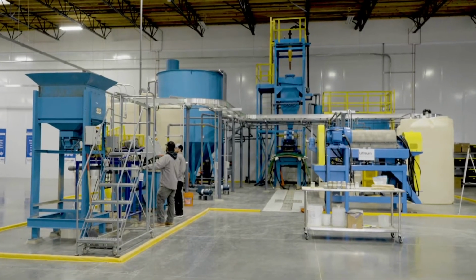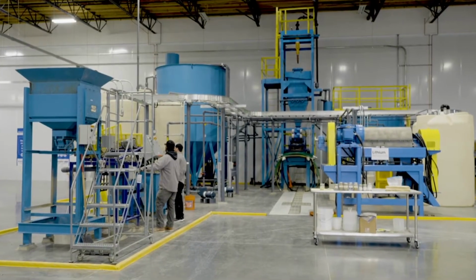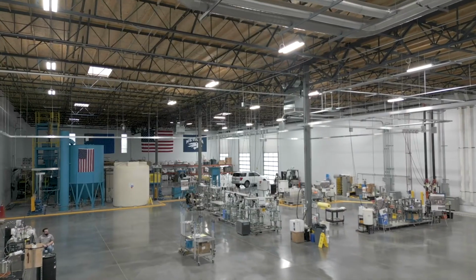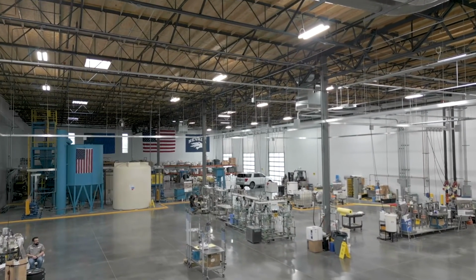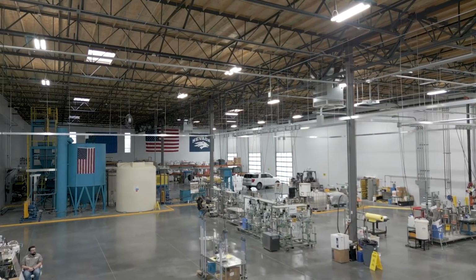The on-site sulfuric acid plant has some very important benefits to our project, principally to our sustainability in the environment. Sulfur is 1/3 of the weight of sulfuric acid. So that means we've reduced the number of trucks on the road by 3. And in addition, the process for sulfuric acid produces a large amount of heat that we capture as steam, feed through a steam turbine, and produce carbon-free electricity, so that we are producing 60% of the electricity required for the process on-site and completely carbon-free. The remaining power that we need comes from the grid, and this is hydroelectric. So Thacker Pass has a completely carbon-free power supply.